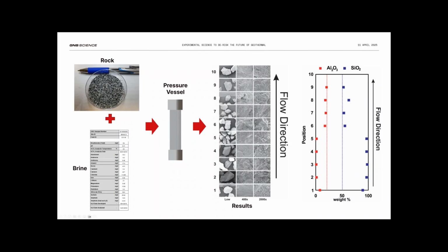So what you see in the middle here is when we take the rock out, sequentially from the bottom to the top, and we divide it into 10 portions. So these positions, you see number 1 to 10, represent the position in the pressure vessel. So 1 is the bottom of the pressure vessel, and that's where the brine enters. And then it passes up through these different layers and exits out the top at position 10. So 1 is where the brine enters, and 10 is where the brine exits. You divide the rock up into 10 portions, and then we do really in-depth sophisticated SEM measurements on the surfaces to determine the surface composition, the average surface composition at each position.